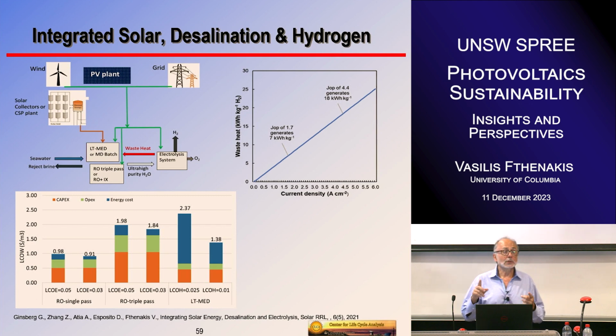And also, I discussed this morning with somebody, I think a PhD student in Greg's group, there is a potential for using solar or waste heat for desalination, to take advantage of the lot of heat released when you dynamically operate electrolyzers. When PEM electrolyzers operate at 1.7 amperes per square centimeter, they release about 7 kilowatt hours per kilo of hydrogen. But when they operate at higher current density, they are less efficient, so they waste more heat. This heat is enough, we found with detailed simulations, to power a solar thermal type of desalination technology, again a thermal technology like low temperature multi-effect distillation, at a lower cost than reverse osmosis.